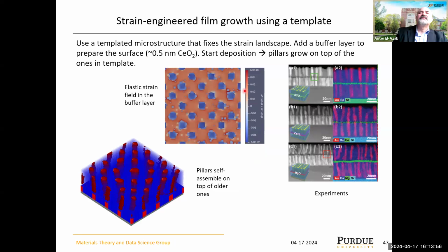And we have used this thing to do so-called strain engineered film growth by looking at templates. These are actual growth morphologies, interrupted growth to put a layer of one phase and then resume the growth again. And the pillars kind of know where they were in the past, and they grow on top of each other. He actually simulated this, and we found that the KMC also kind of recognizes where these things are. In order to do this, you have to know the strain, because the pillars under this green layer communicate with the newer ones through the strain effect. Without the strain effect, you won't know this. These things will not know that there were pillars grown before in the system.